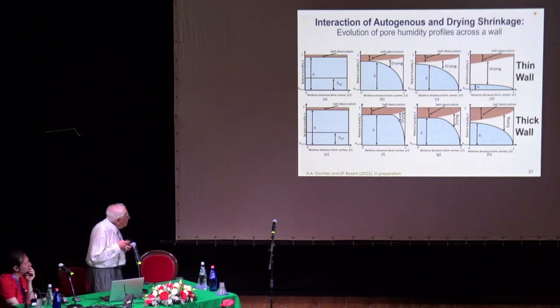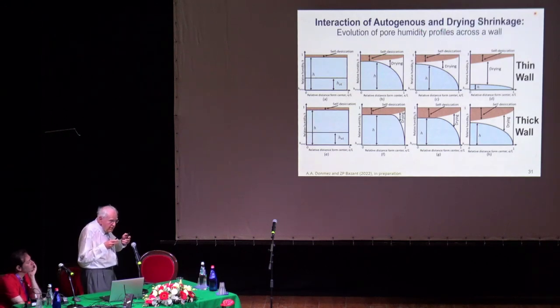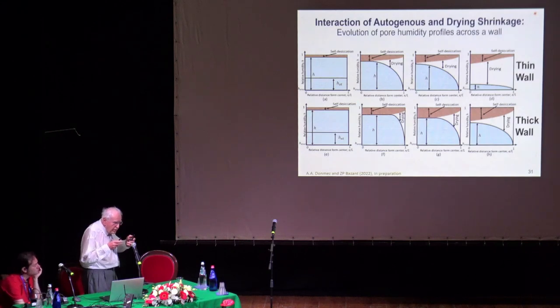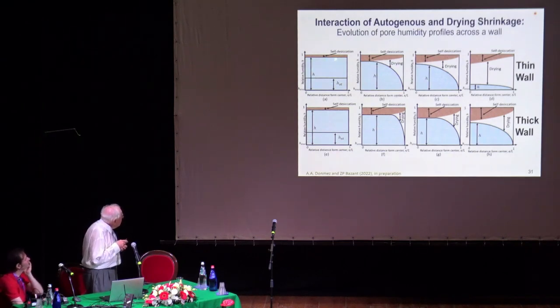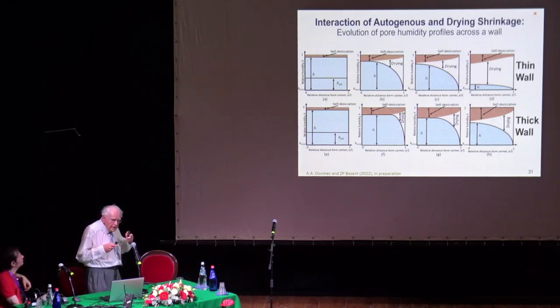And that causes large autogenous shrinkage, where a sealed specimen would decrease the humidity in the pores not to 98% but to 60%. That produces enormous autogenous shrinkage, as big as drying shrinkage, and they interact with the drying from the side. And this is different for thin and large walls. So in a thin wall, you have saturation by water, this is self-desiccation, but the self-desiccation rate depends on humidity. If the humidity goes down, it slows down.